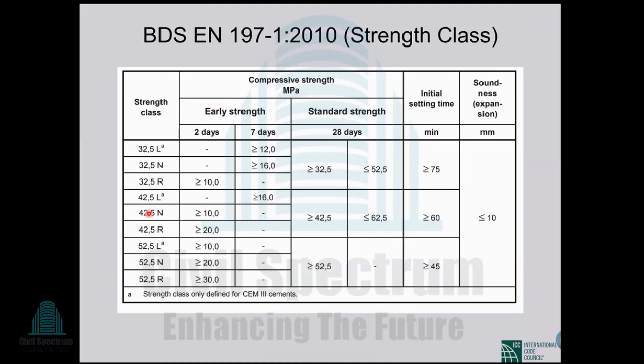So 2 days, in case of N, it must be more than 10 megapascal for 42.5, and for R variety, it must be more than 20 megapascal. Oh, sorry. In 52.5, in case of N, it must be more than 20 megapascal. And in case of R, it must be more than 30 megapascal.